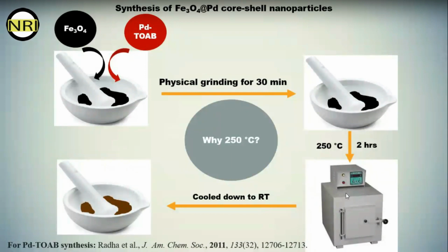So what I have done is, I mixed Fe3O4 and palladium TOABr in a mortar and pestle and ground them for 30 minutes to get a homogeneous mixture of palladium TOABr over Fe3O4. Then I heated that solid mixture at 250 degrees C for 2 hours in a muffle furnace. After cooling down to room temperature, I collected the catalyst.